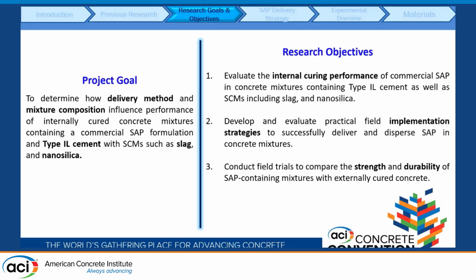Now, the goal of this research is to determine the delivery method, as well as the mixture composition, and how it influences the performance of internally cured concrete mixtures containing superabsorbent polymer, that's commercial superabsorbent polymer formulation, and type 1L cement, and supplementary cementitious materials such as slag and nanosilica. To do this, our objective is to evaluate the internal curing performance of the commercial SAP in concrete, and also evaluate the practical field implementation strategy to successfully deliver and disperse SAP in concrete mixtures, and then conduct field trials to compare the strength and durability of SAP containing mixtures with externally cured ones.